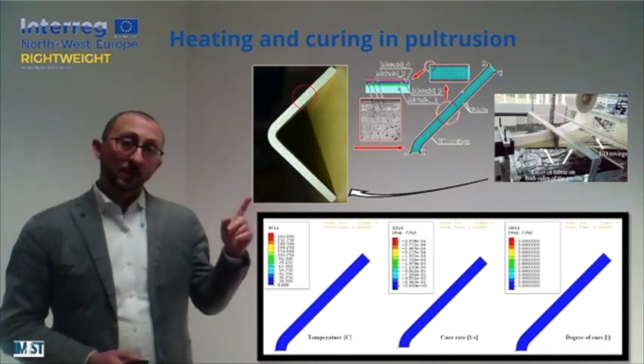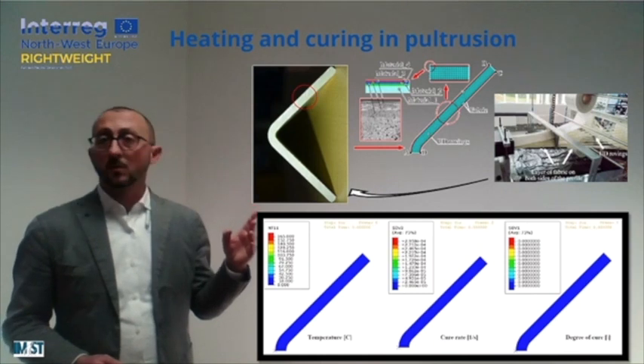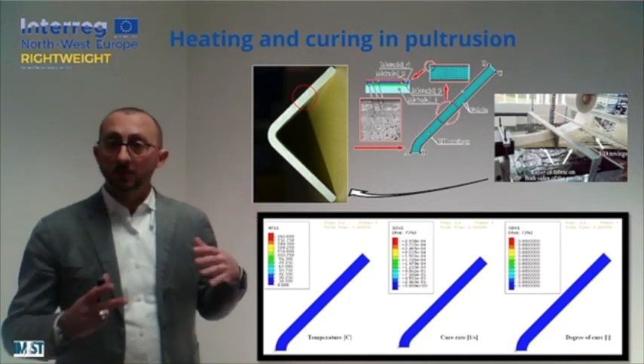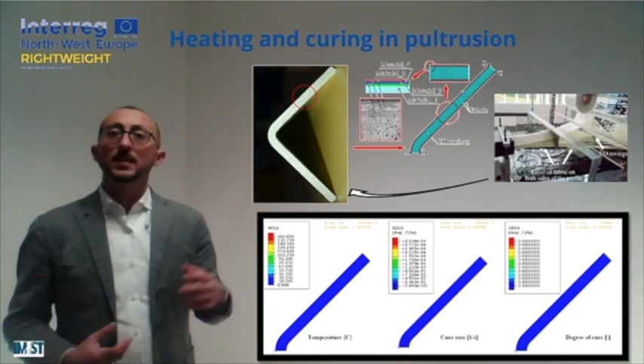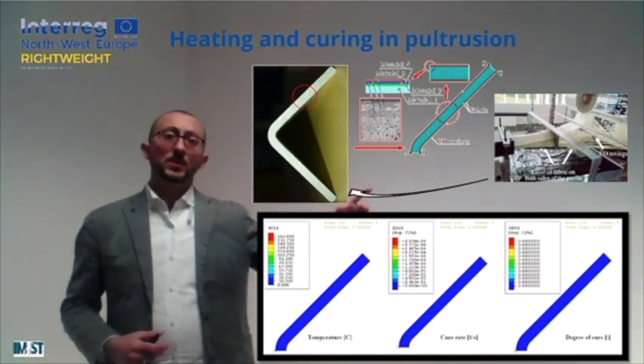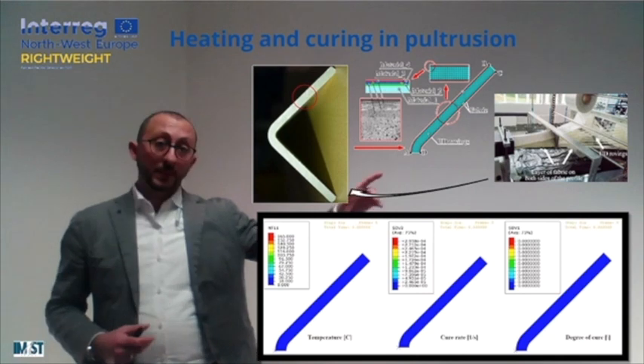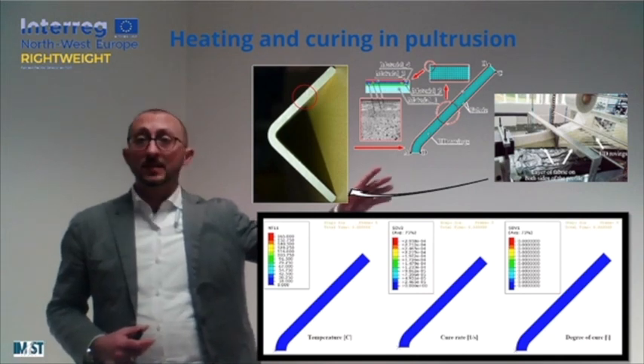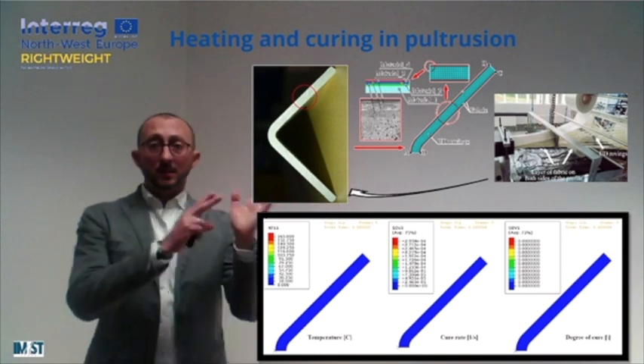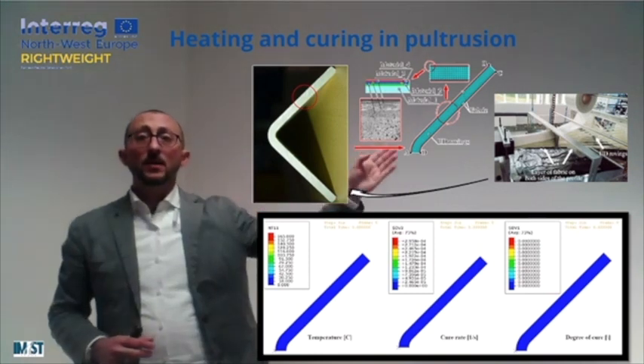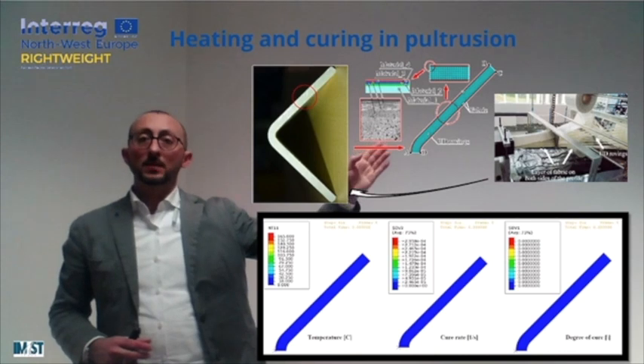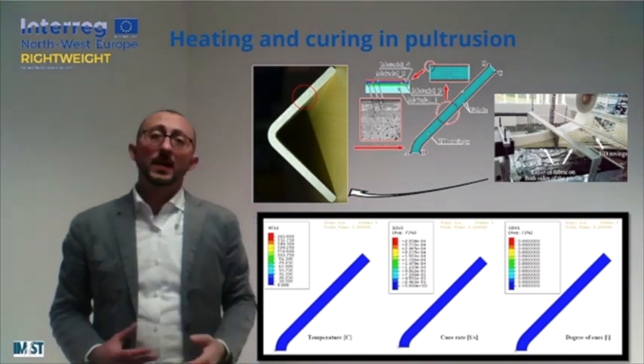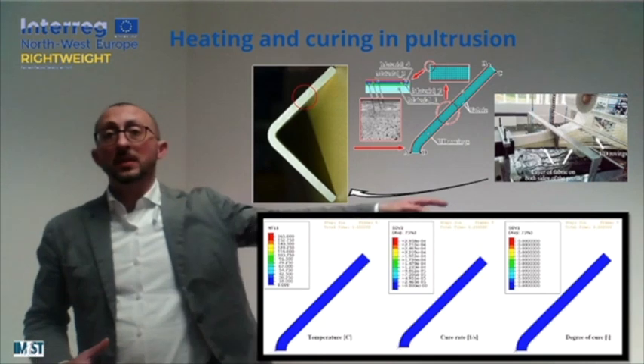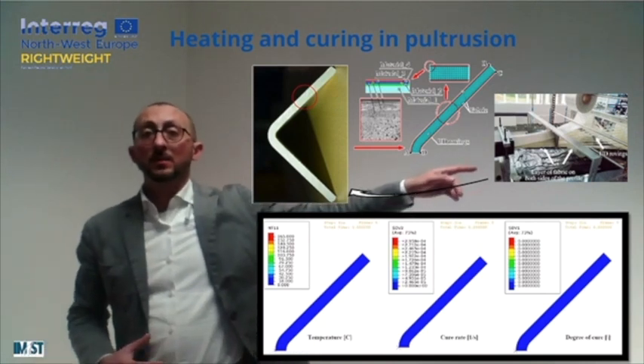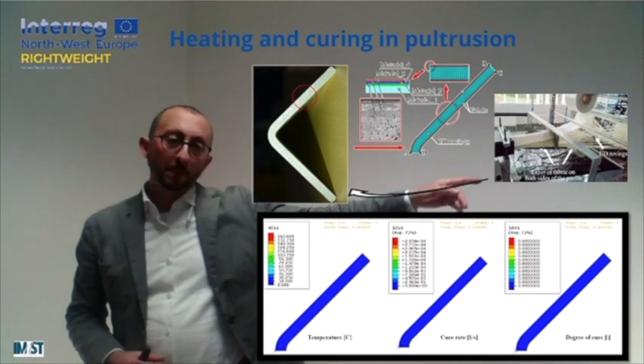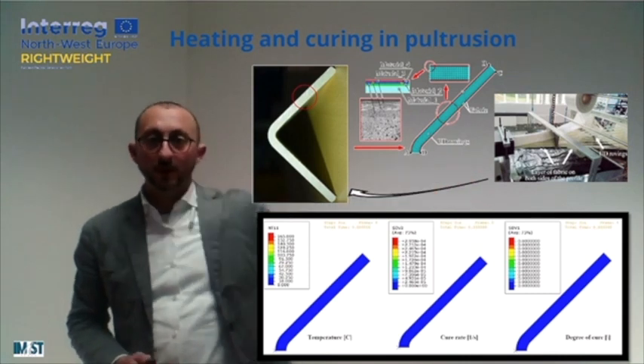In this case, our profile is quite good in order to understand also something about the distortion of the material inside the heating die. Just a few words about our material. The reinforcement is a combination of unidirectional fibers in the core of this L, and then moving to the surfaces, we will have a combination of mat and woven fabric. So the real process is depicted here. It will give you a very good representation of what is going on.